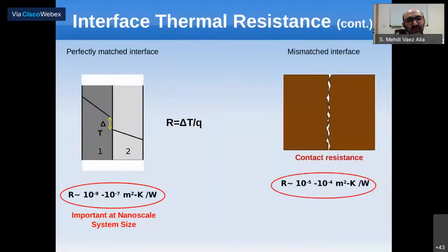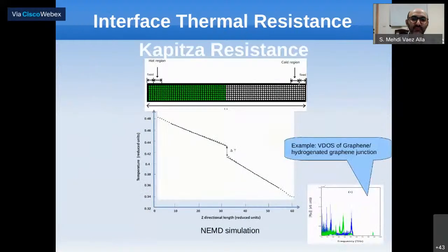What happens if we have an interface? We have Kapitza resistance, as you see here. If we put hot and cold heat baths at the two sides, following Fourier's law, we consider a very flat, very straight graph from the hot to the cold. This is the temperature profile. But at the interface, we have a gap called Kapitza resistance. Something happens due to the phonon scattering in the middle of the system.